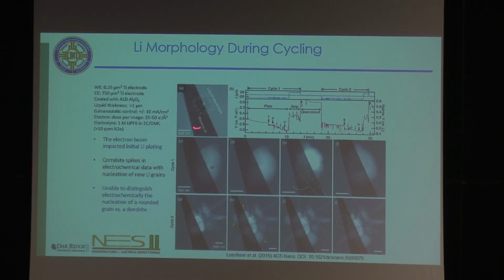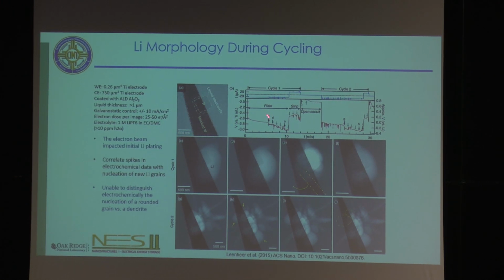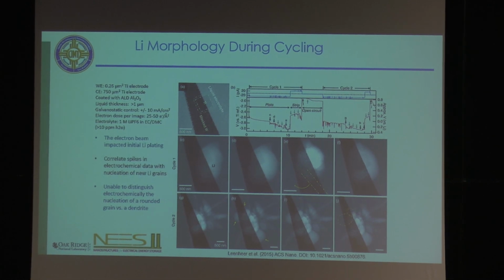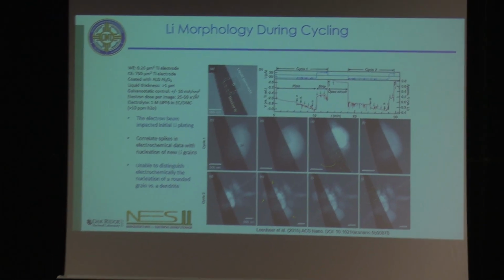All right, so here's the starting condition. Here's C as you start to deposit the lithium, and that corresponds to this little arrow right here. So that was the first image. The first TEM image was taken at that point. You had a nice smooth curve, so the deposition was going well.